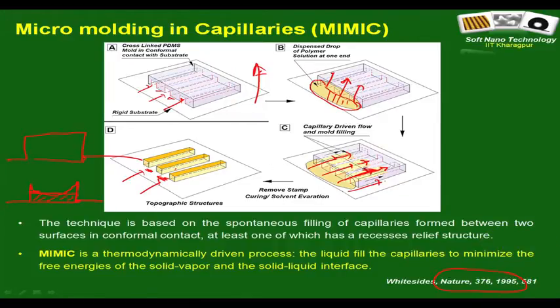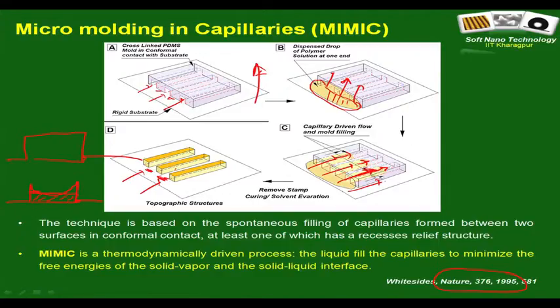Why does this thing happen? Because during the capillary driven flow, as shown in this particular step, the flow is taking place with a dilute solution, right, and therefore the channels are filled with a dilute solution. So, once you feel that the capillary dynamics is over, and eventually the solvent evaporates away, there is going to be significant loss in dimension because of the shrinkage, because of the evaporation.